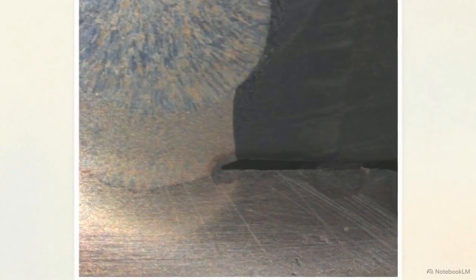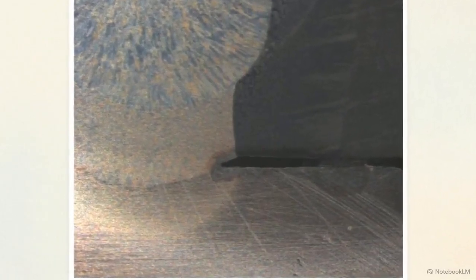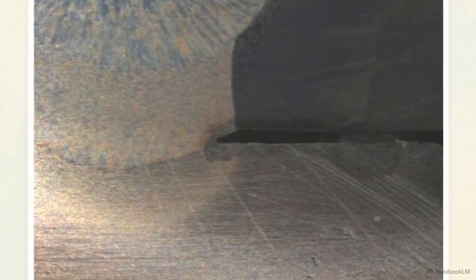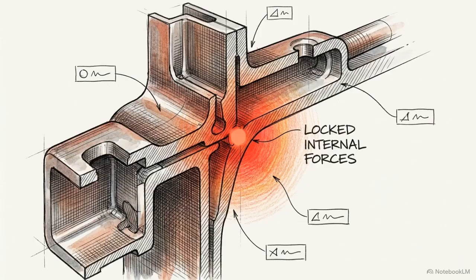Looking at this high-magnification image, the trajectory of the failure becomes clear. The main fatigue crack originates directly inside the softer, unaffected base metal. It travels straight through the base material, ignoring the heat-affected zone. This trajectory defies standard rules of geometric stress concentration. With the material verified as sound, a localized force is artificially elevating the stress state within the base metal, a characteristic signature of residual thermal stress.